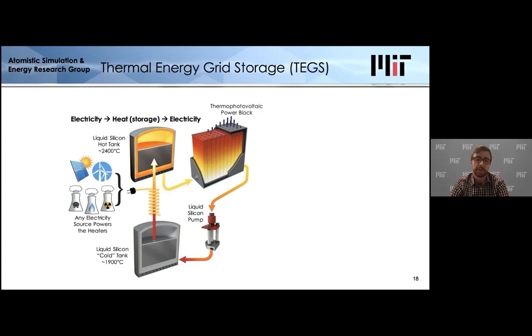So the way this system works is you have a cold silicon tank filled with molten silicon at around 1900 degrees Celsius, and a hot silicon tank filled with molten silicon at around 2400 Celsius. When you have excess power on the grid, you heat the cold silicon and pump it to the hot tank. And when you require power, you pump this hot liquid through a thermophotovoltaic power block. This thermophotovoltaic power block converts the heat to electricity, and that can be provided back to the grid and address any intermittency in renewables.